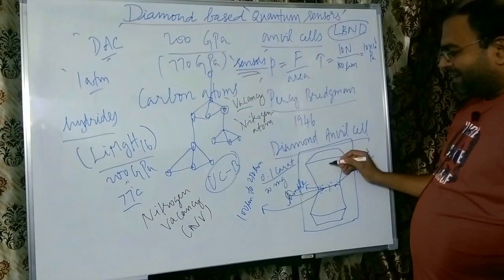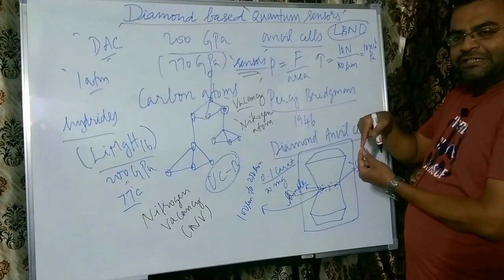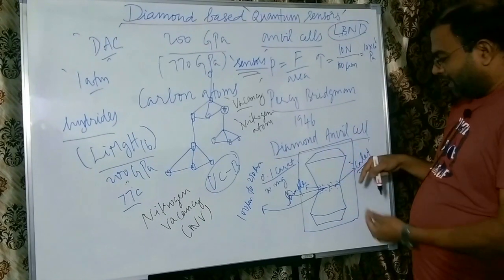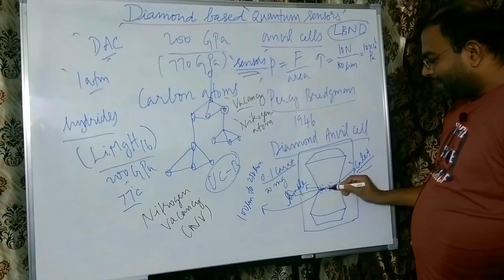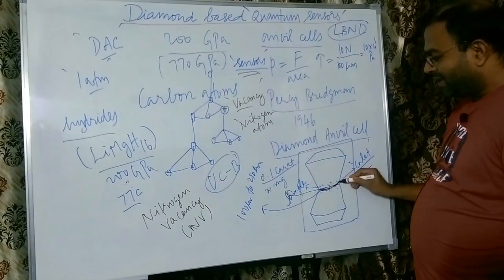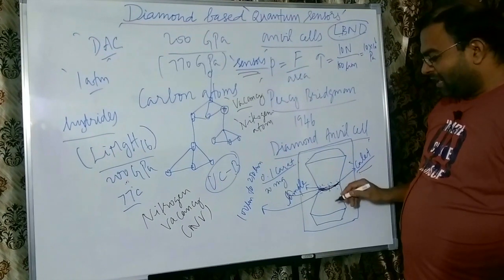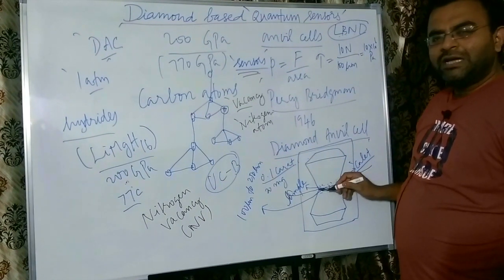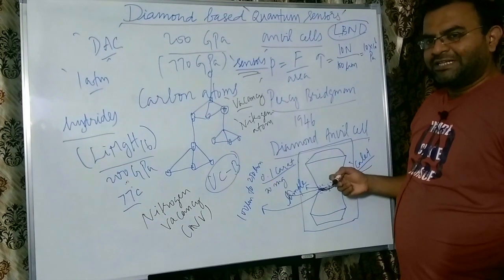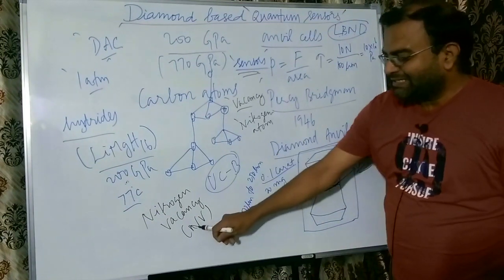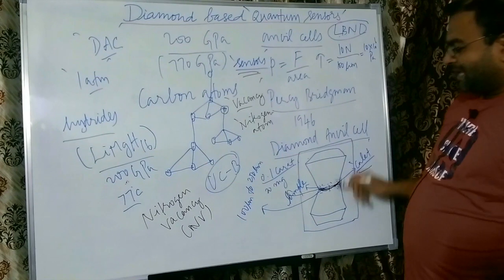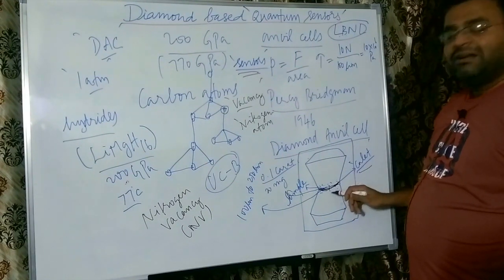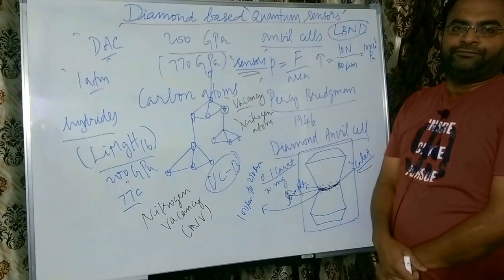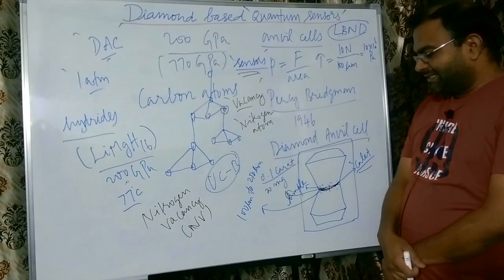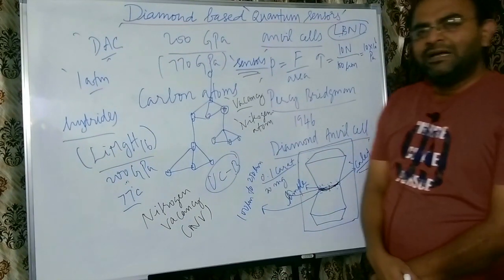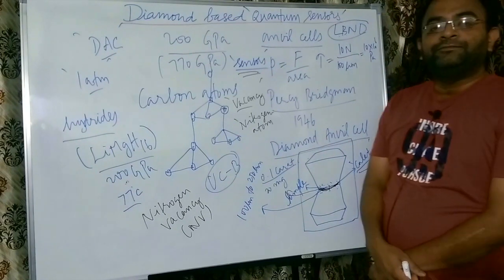For example, whenever pressure is applied onto the diamond pieces in the anvil cell, there is going to be what is called a cupping effect. That is, there is going to be an inward curvature of the cell, and this could not be observed at low pressures under normal circumstances. But with the presence of these nitrogen vacancies, these scientists have been able to see this cupping behavior even at low pressures. This is an interesting result that has emerged out of their study.